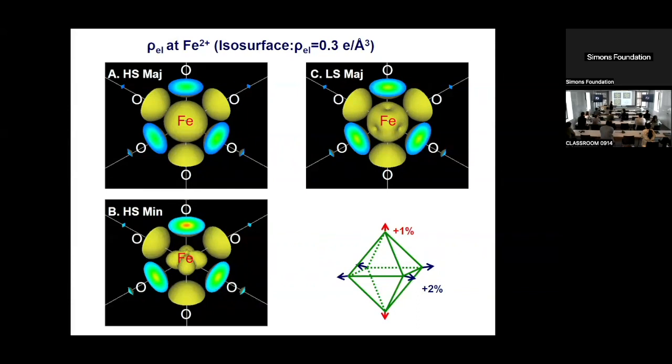Okay. So Mössbauer quadrupole splitting: iron Mössbauer spectroscopy is what's used to determine these spin states experimentally. When you replace magnesium by high spin iron, the octahedron expands non-isotropically because of the Jahn-Teller distortion, with the minority electron spin down. And when you replace it with the low spin state, it contracts. So across the high spin to low spin change, you have a contraction of the ferropericlase octahedron by 8%. This is huge.